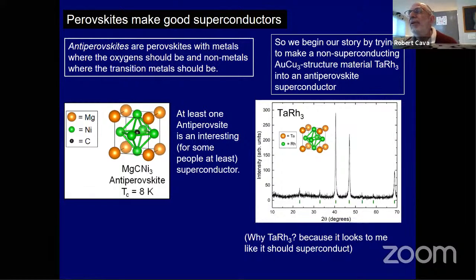Another electropositive element is something like tantalum. It's very electropositive, meaning it really likes to donate electrons to things. So I thought tantalum, rhodium-3, boron should be a superconductor. Duh. I mean, that's basically the whole logic that went into that, because it has an electropositive element, something under something that might accept electrons in a polar intermetallic compound like rhodium. And then maybe you could put something in this hole right here.